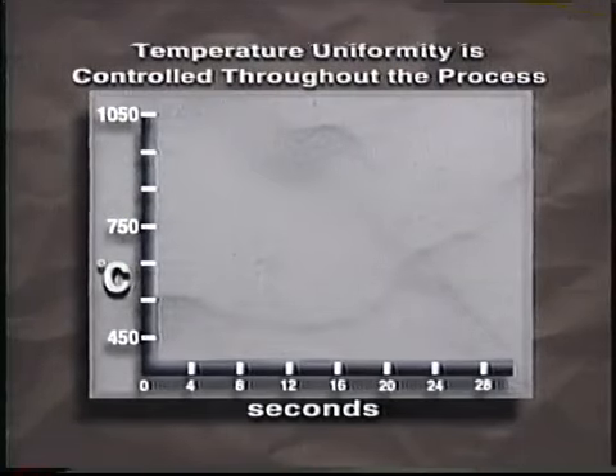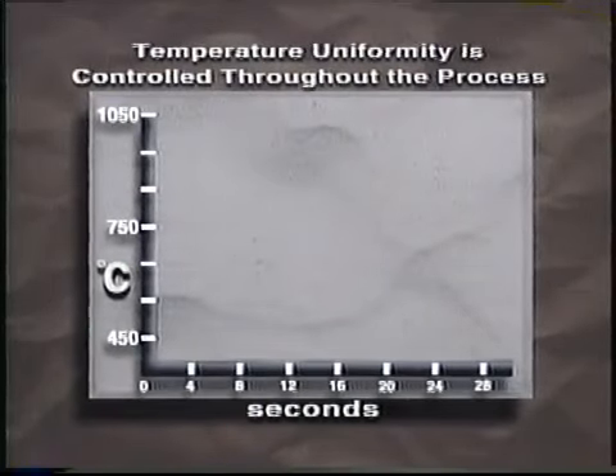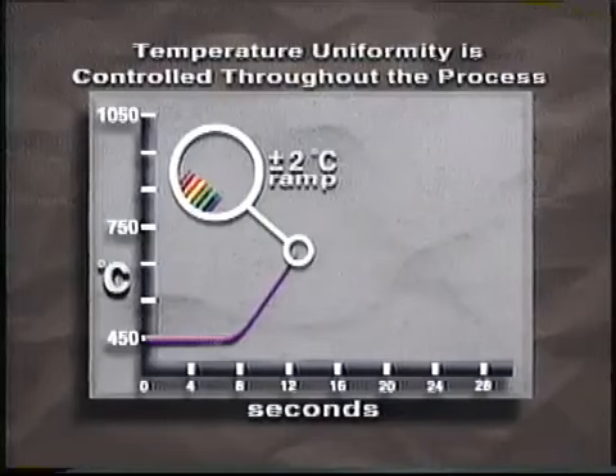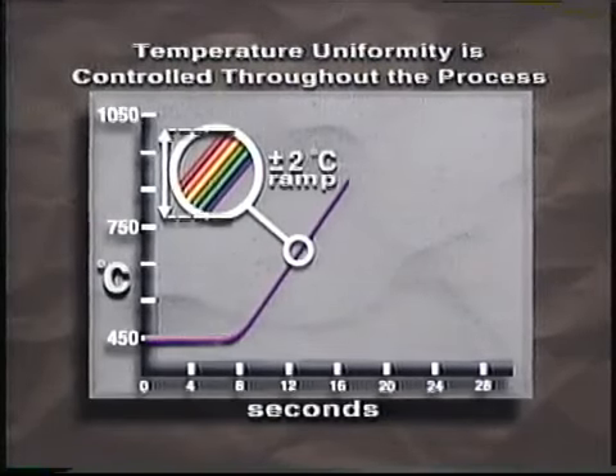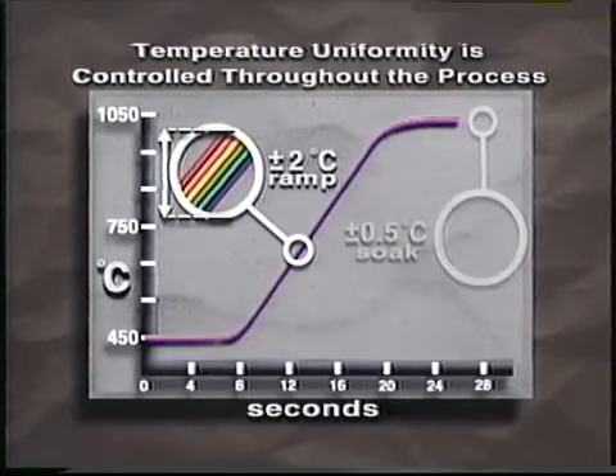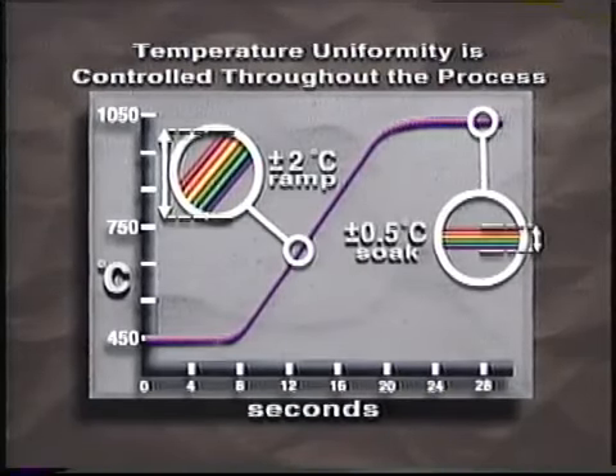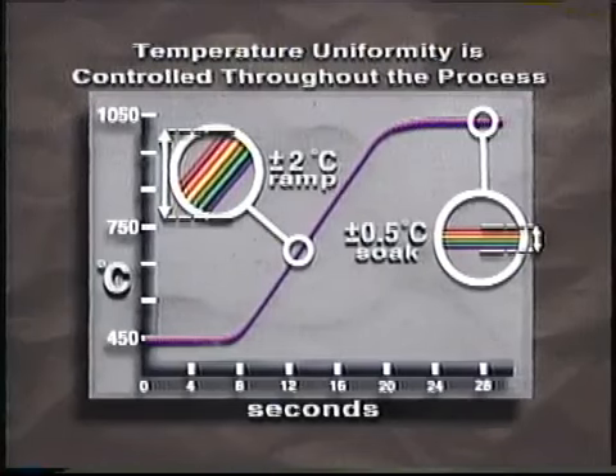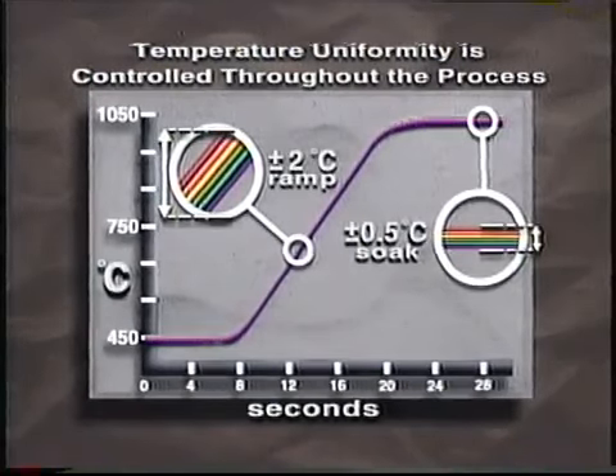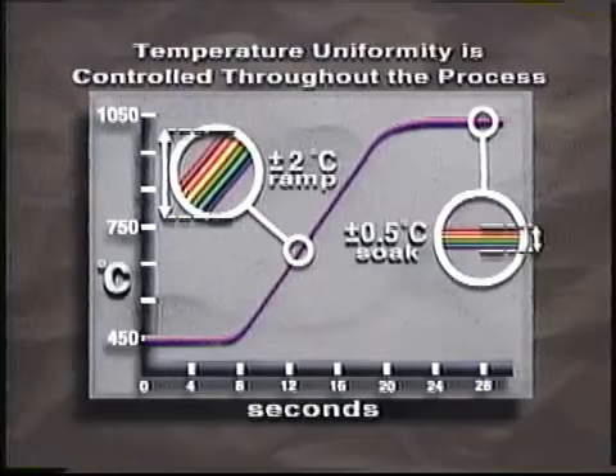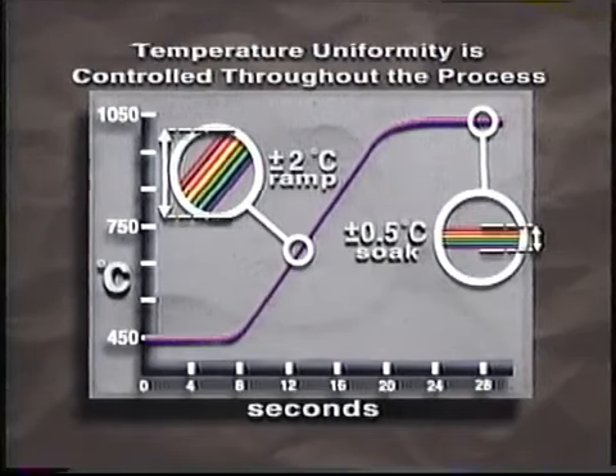The RTP chamber has a programmable variable temperature ramping capability of up to 75 degrees C per second, with a ramp uniformity of better than plus or minus 2 degrees C. Steady state temperature uniformity is typically better than plus or minus 0.5 degrees C. The result is the most uniform thermal wafer processing possible in the industry today, and a process that's guaranteed to be free of lattice slip defects.